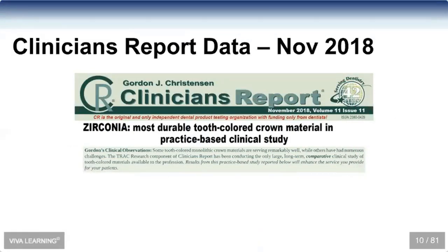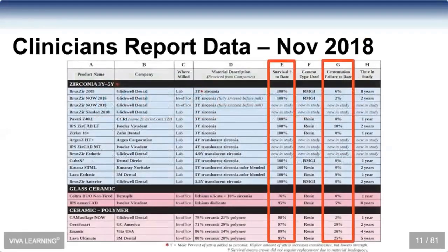If we look at the work that Gordon's been, well, it's not Gordon, it's really Rella's been doing up at the TRAC Foundation. In 2018, they released their newest issue of the report that's been looking at zirconia and Emax in their study that started back in 2009. I've highlighted a couple of columns here, this survival to date. You can see at the top, BruxZir 2009 has a survival rate of 100%, and cementation failure of 6%, which isn't surprising because we didn't know that much about the salivary contamination of zirconia back in those days.